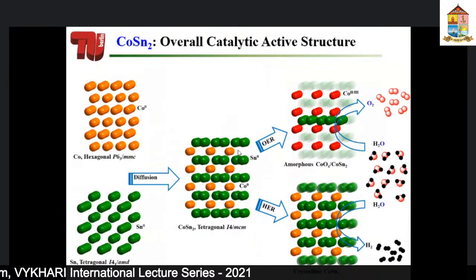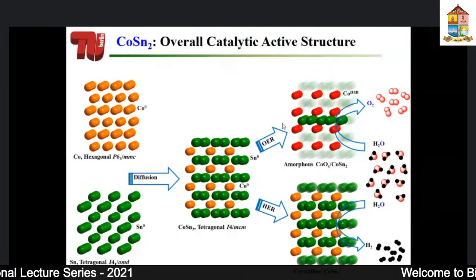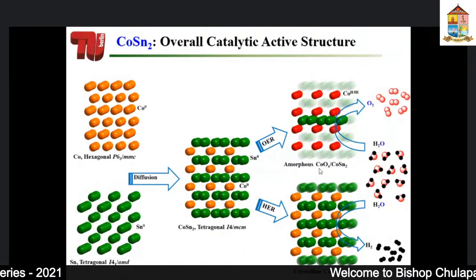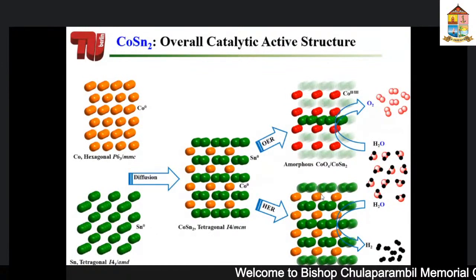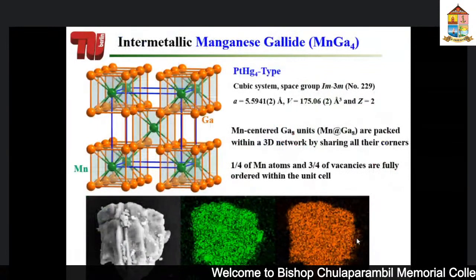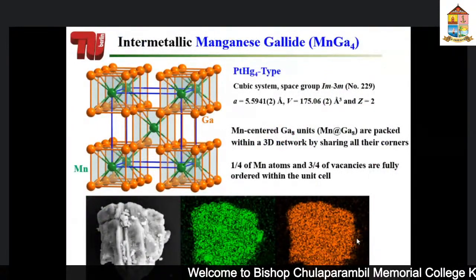To show you a complete overview, we started with cobalt tin, and we formed a cobalt tin 2 structure by controlling the composition. And what we show is that during the oxygen evolution reaction, the catalyst doesn't remain constant or stable. It completely undergoes reconstruction to form such a cobalt oxide structure, with cobalt tin 2 remaining in a very small amount, whereas in the case of the hydrogen evolution reaction, it is almost stable. Okay, I think I do not have time to show you more